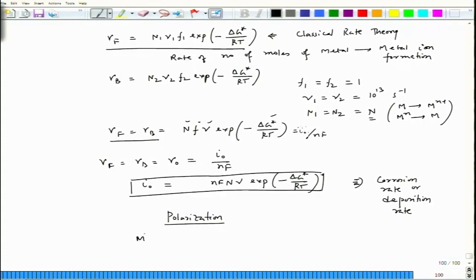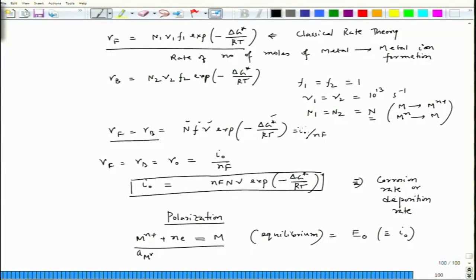Now, we see that when M n plus plus n e M, this is reaching equilibrium, so we have a potential, which is of course giving a situation of I 0, which is exchange current density, and if we have maintained standard value, it would be E 0. So, that means activity of M n plus equal to 1, temperature equal to 25 degrees Celsius and pressure equal to 1 atmosphere pressure. So, then it becomes E 0, E 0.